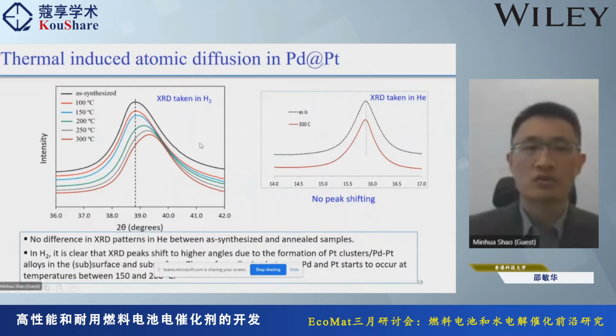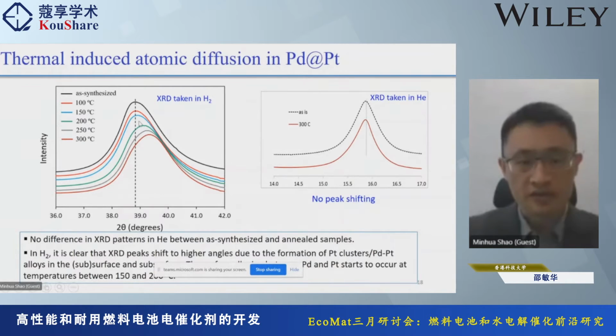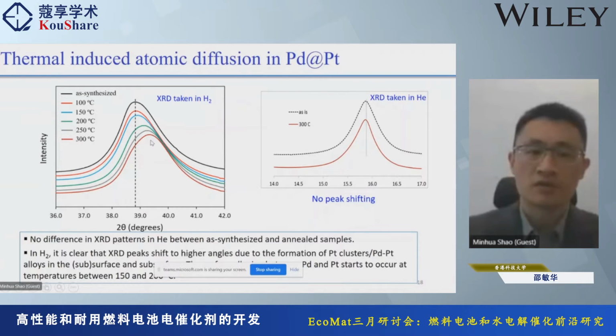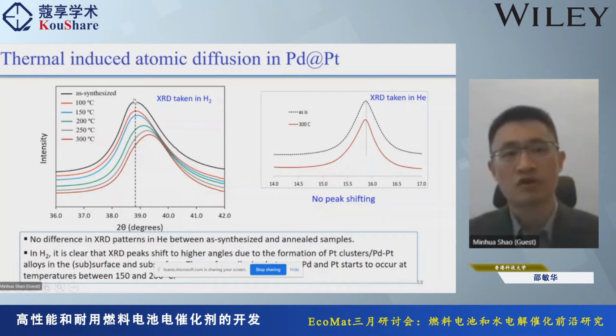We also did this using in situ XRD. We can see that in hydrogen, starting at about 150 Celsius, we started to see the peak shifting. It's not as clear as the as-synthesized material. And at 300 Celsius, for most of the material, the peak is not shifting. This is reasonable because if you form an alloy shell instead of a pure platinum shell, the hydrogen does not diffuse easily into this palladium core, causing the peak shifting to not be as clear as in the core shell structure.